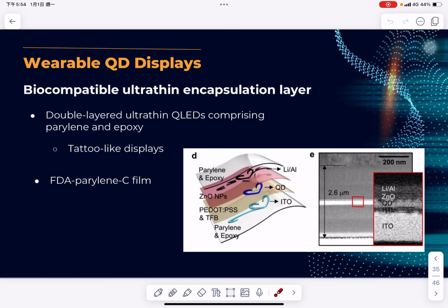Cho developed a double-layered ultra-thin QLED for a skin-friendly display. You can see the structure here. FDA-approved Parylene C prevents skin issues, while the thin epoxy protects it during sputtering. The total encapsulation is 1.2 micrometers, yielding a QLED thickness of 2.6 micrometers.